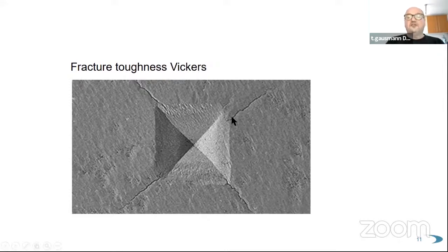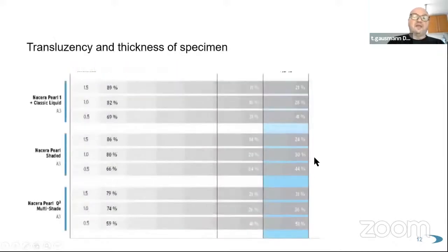The point is, you can't see the beginning of the crack, and you can't see the end of the crack. You need a very, very good microscope, and this is something that nobody uses. They know this, but they don't use it. And you can't really see where the source of the crack is. When you can't see the source of the crack, you can't tell the line is this long, and it's not valid either. So it's another problem with the testing.